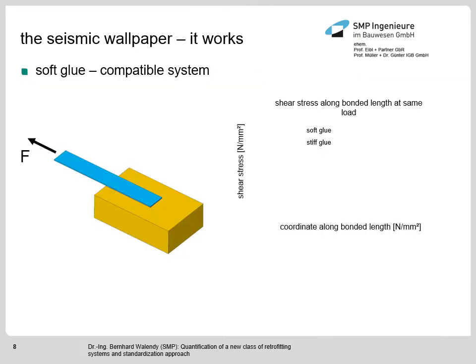Let's have a quick look at the basic principles. Why do soft glues actually behave so well for masonry systems? Remember, the standard failure mode is a cohesive and a very brittle failure mode, which is governed by the tensile strength of the masonry stone. And the key in order to improve the mechanical properties of the applied textile retrofitting systems is to reduce maximum shear stress peaks which are transferred between the textile retrofitting system and the masonry block.